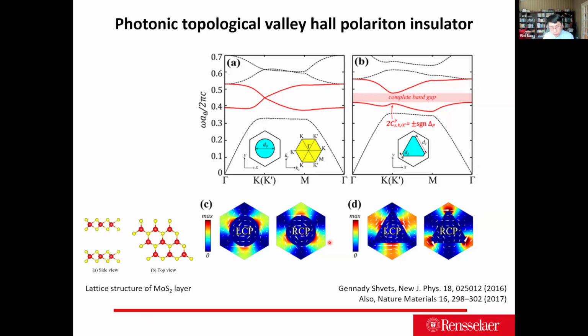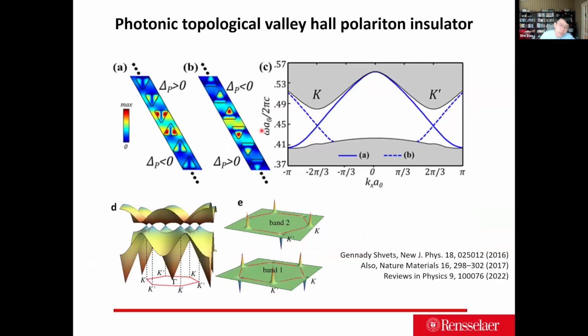And this is sensitive to right-hand circularly polarized light and left-hand circularly polarized light. Those are the simulations. If you bring the two small photonic atoms together, you will have a type A topological edge state, which is the solid curve. These are the two valleys. If you have the two big atoms arranged next to each other, you will have the type B topological edge state along the dashed line. The good thing is the type B has a slightly tighter confinement on the edge, while the type A is a little bit more spread out across the edge.